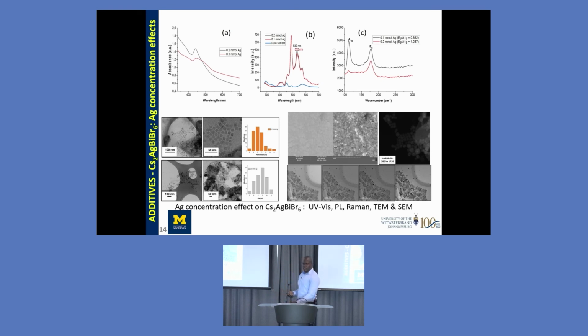So some additives could also be used in order to improve the properties of prepared nanocrystals or perovskite in this specific case. So cesium bismuth bromide, for example, had limited stability. But by choosing to add some additives, in this specific case, we chose silver. Silver was chosen because of its excellent optical properties. So we use a small amount of silver as additive. When you add it, then you see that the optical properties are really very good. And indeed, the amounts were very small. If you take 0.2, even half that amount, you still have very good properties.